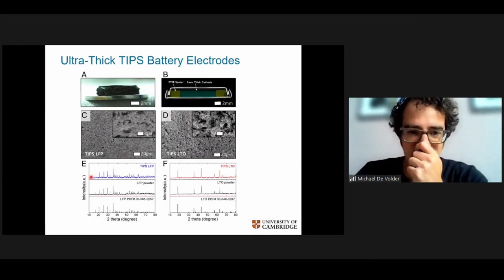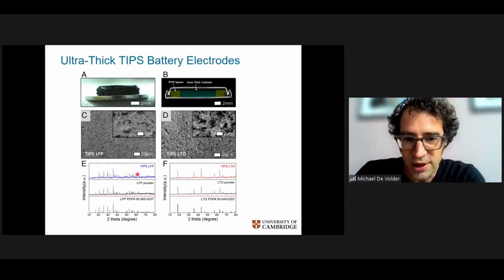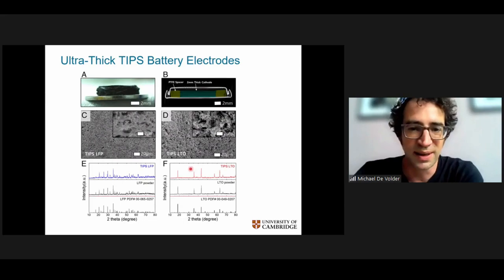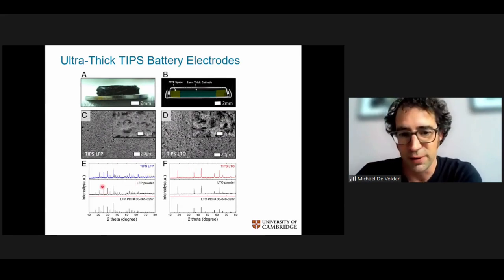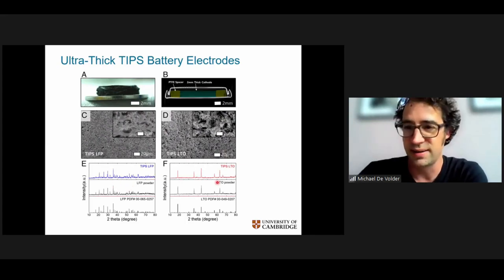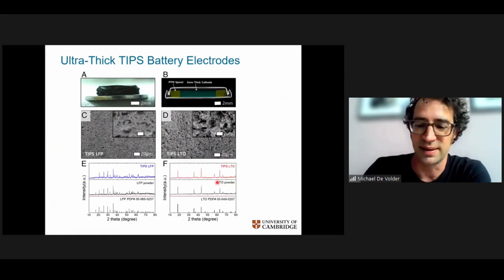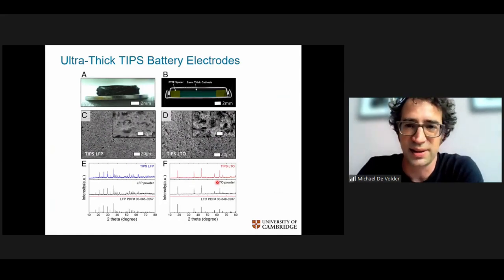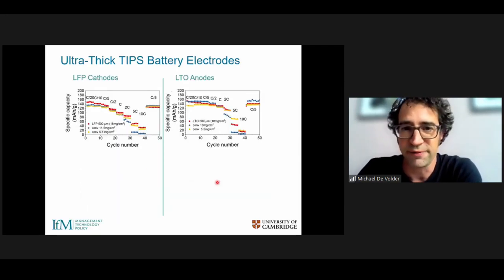And so you can see at the top the X-ray diffraction patterns of our materials before coating the battery material and then after. And if you compare those two graphs, you can see that there's actually no difference before and after the phase segregation process, which means that the little houses for lithium ions are not damaged by the process. Then the next thing we did is we tested the performance of our batteries.